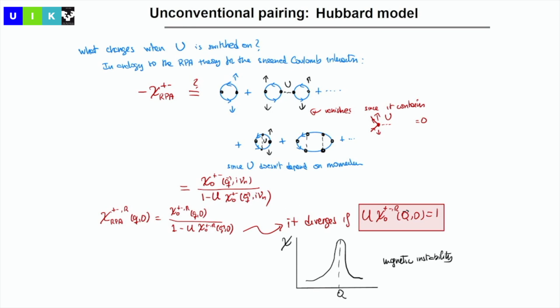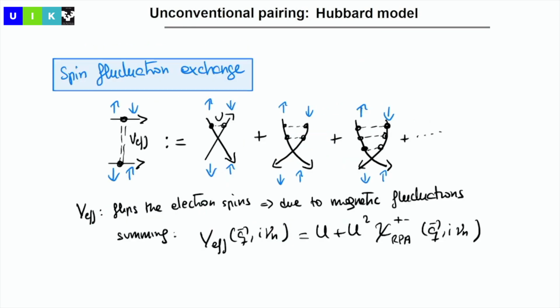Now, of course, what is interesting is that this interacting susceptibility has a divergence, as you see, when the denominator goes to 0. And this divergence is related to the magnetic instability you expect in the system. If you do that for the square lattice I was showing you at half filling, it gives you the magnetic instability precisely at (pi, pi), which is the antiferromagnetic order, which is what we know happens in the cuprates when they are half-filled in the parent compound. So with this kind of calculation, we already have information about where our instabilities are, and this is going to come into the equation of our effective interaction.